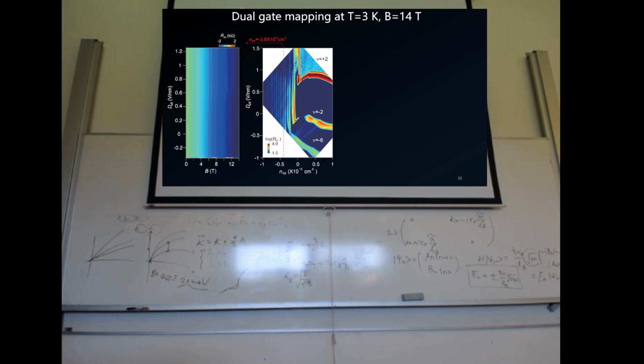For example, on the left hand side, if we make a line cut along this red dashed line and run the measurement from 0 magnetic field to 14 Tesla, and make a map using the displacement field and the magnetic field as parameters, you will see the conventional graphene Landau levels or SdH oscillations, which start at a few Tesla and then develop into quantum Hall plateaus. This is very conventional and as usual, okay?